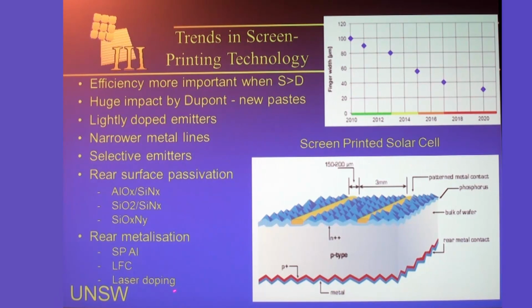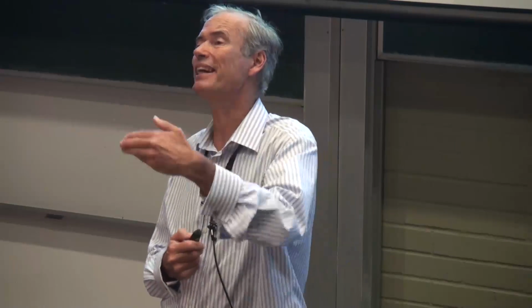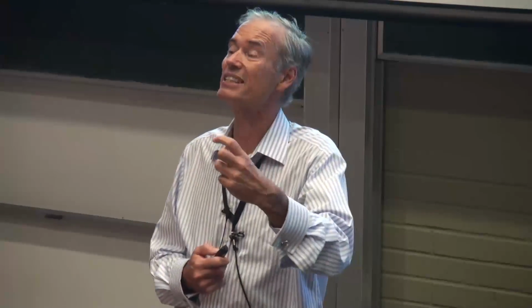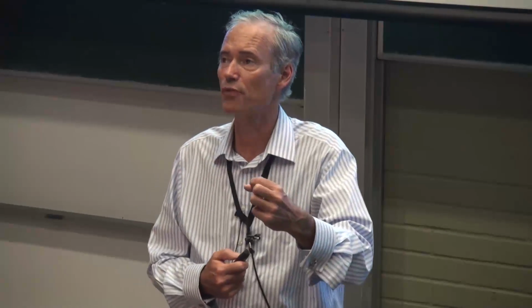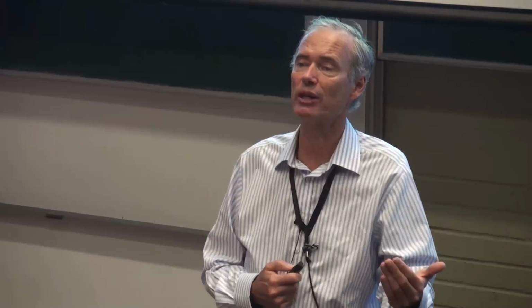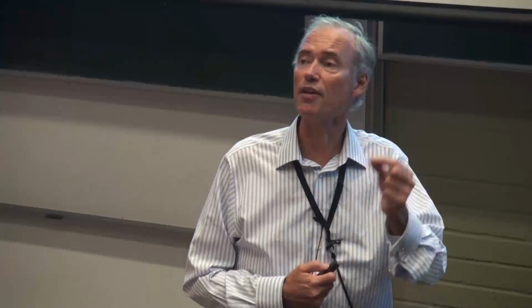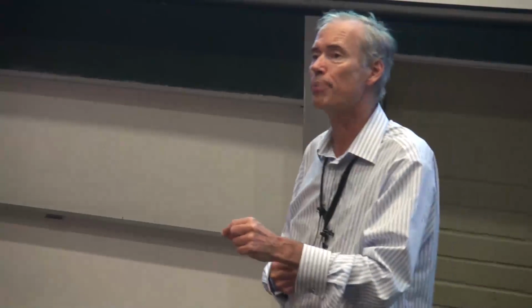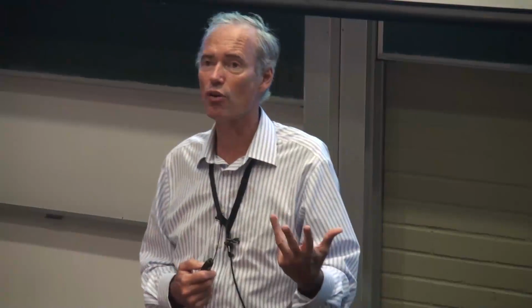And then the other approach is laser doping. So an approach that some companies are very seriously looking at now is that they use a laser not only to pattern the dielectric layer on the back, but to simultaneously dope the silicon to form a localized back surface field region. And if you do that, it then increases the options that you have with how to put the metal on the back. Because if you form your P+ regions in those localized areas, independent of the screen printing alloying process, you can then, if you want to, use a lower temperature metal deposition such as sputtered aluminium or E-beam evaporated aluminium, etc., which then only needs a low temperature sinter. And there's certainly some companies that believe that that low temperature process is a very important part of getting the best hydrogenation benefits out of the silicon wafers.